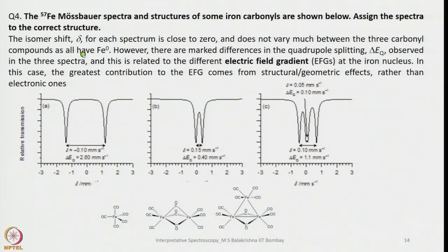The isomer shift, delta, for each spectrum is close to zero and does not vary much between the three carbonyl compounds, because all of them have a 3d6 4s2 electronic configuration. Iron is in the zero state. However, there are marked differences in the quadrupole splitting.